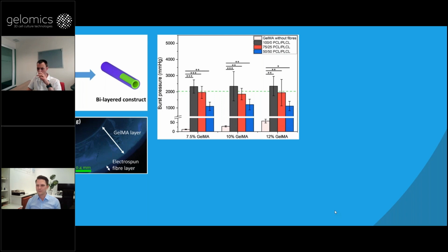Ferry, Professor Travis Klein from QUT, and Peter Levett, and myself, we've all been working in the cartilage tissue engineering field. And we haven't really focused so much on using stem cells, but primary chondrocytes, so the cartilage cells directly from a donor or patient. And we've incorporated this in GelMA, sometimes GelMA with hyaluronic acid. And what we found is that these cells would really develop and grow into neocartilage constructs over time quite significantly. So there was a significant accumulation of cartilage-specific proteins and macromolecules. And in terms of mechanical properties, we really saw that these increased quite significantly over time. So within a month, we typically saw something around 2 to 3 times the mechanical properties compared to the initial start date. That's for pure GelMA gels.